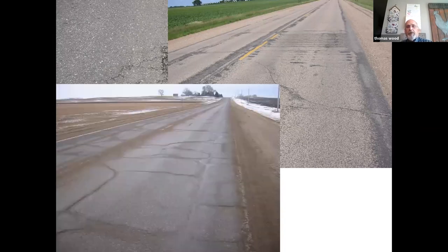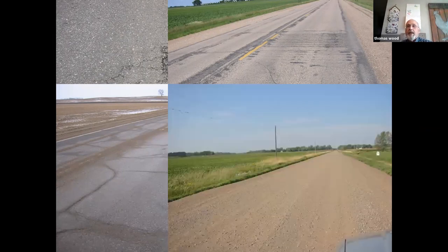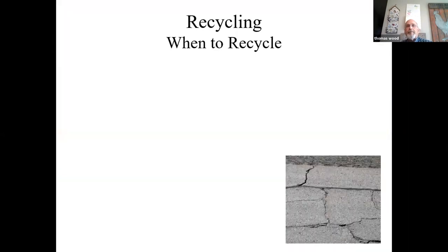Remember the picture of the road with the quarter that I showed just a few clicks back? Well, this is how that road looks when you're sitting in the truck. When you first look at it, you go, oh, that's not terrible. I mean, it's not good, but it's not terrible. But then you look up close and you see how bad. And one interesting area, especially with FDR and SFDR, is we can modify gravel roads to allow us to pave them with a thinner hot mix surface to get the people out of the dust.